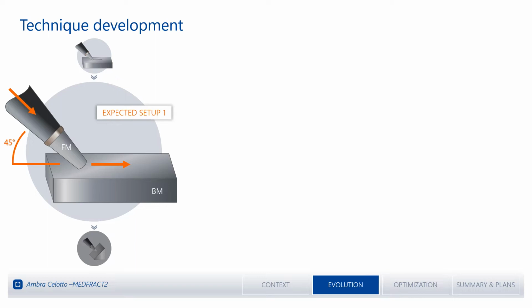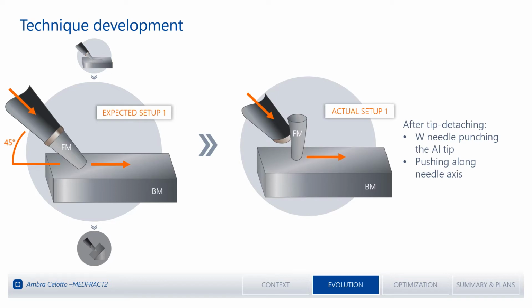This made us change the geometry of our setup, and we did it by creating a thicker aluminum tip for the hybrid needle that was meant to be smeared onto the base metal that has no groove at all. So basically this was the expected setup. But in reality, what occurred is that the absence of any groove, any guide for the filler metal to be spread into, led the tip to detach from the tungsten needle. And the tungsten needle actually worked as a punch for this filler metal to be spread onto the base metal.